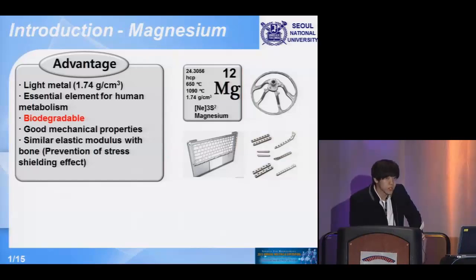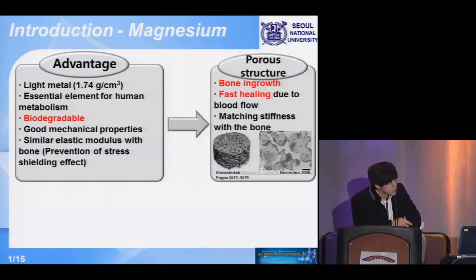And it has a similar elastic modulus to that of the bone, so there is less possibility for the stress shielding effect to happen. So if we make this magnesium into a porous structure, the cells would easily go inside the pores and fix the implant with the surrounding tissues. And also, due to the blood flow through the pores, healing would be much faster.